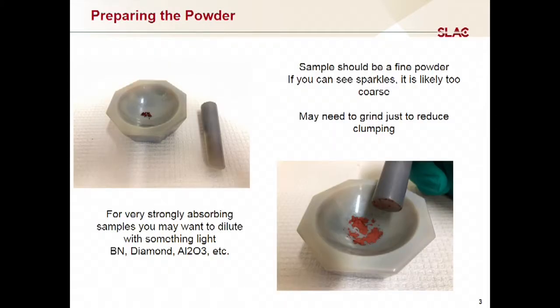So step 1, of course, is I have some powder, and I want to make sure that it's a good powder for measuring. And so there's a couple of things that you want to keep in mind. One, it should be a pretty fine powder. So if you look at this and sort of move it around, and you can see some sparkle from large crystallites. If you think about something like granulated sugar, you move it around, you can usually see it sparkle. That is bad. That means that you have crystals that are too large, really, for what you want. And so you should try to grind that up to make them smaller.